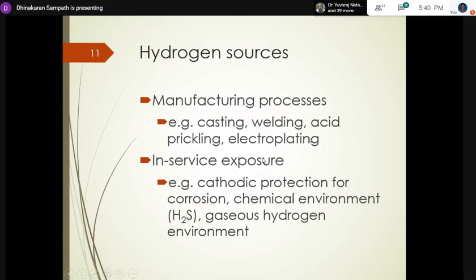And in-service exposure is very complicated because hydrogen is there throughout the life of the material in service. A few examples are cathodic protection for corrosion of the material. Actually, sometimes it will hit over potential, which leads to hydrogen generation in excess. And some people say even in air, due to moisture, we'll have hydrogen going into the material, but it depends on it; once it reaches some critical concentration, it'll also be detrimental. And as I told, gaseous hydrogen environment.